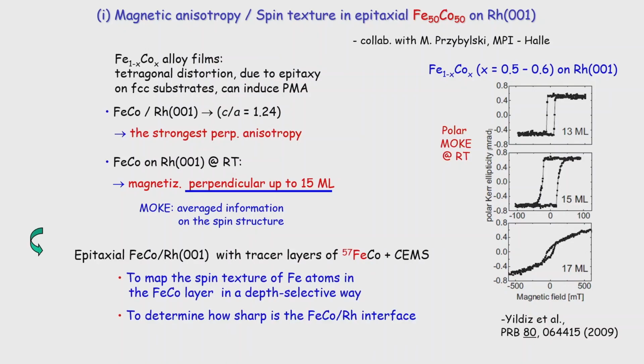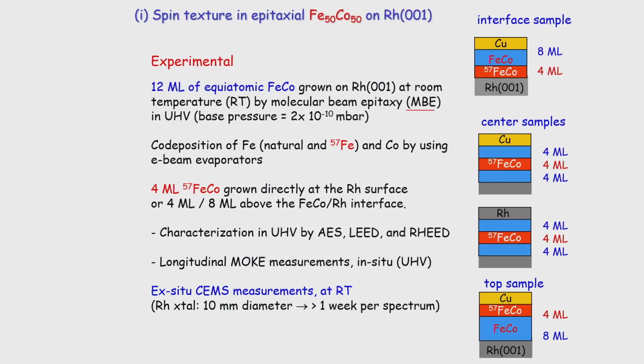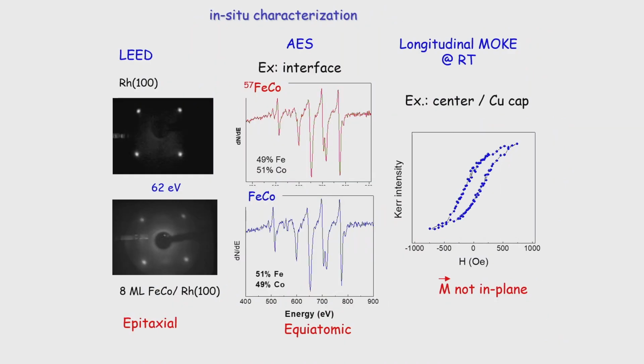They want to see what happens really along these 15 monolayers by using iron 57 probe layers. We did that years ago by always growing 12 monolayers of iron cobalt by co-deposition, okay, and always putting 4 monolayers of iron 57 cobalt at different positions of these stacks. The important thing is that you have to know the sample you have, okay?